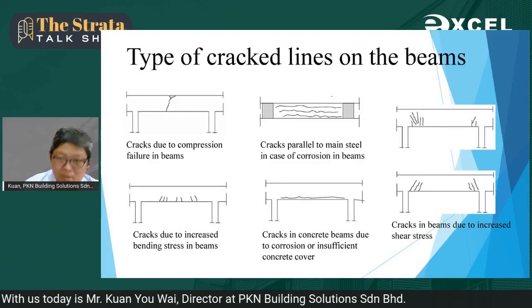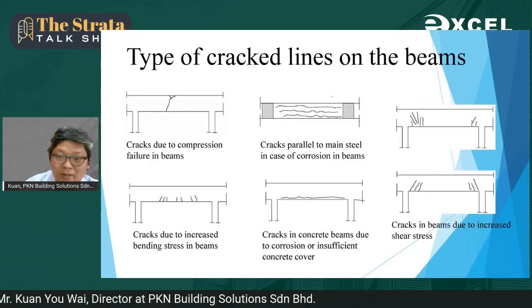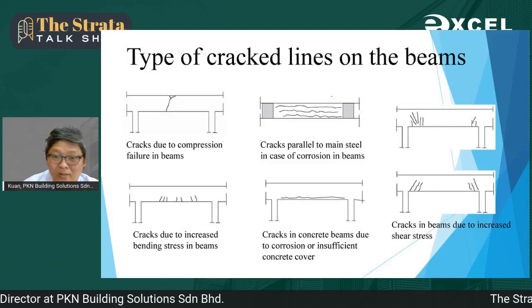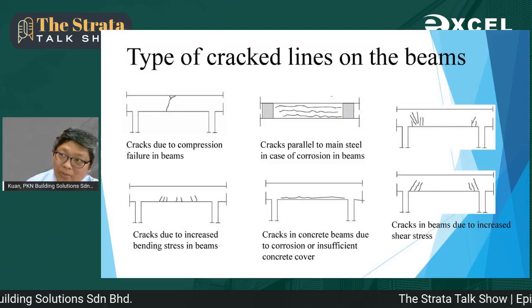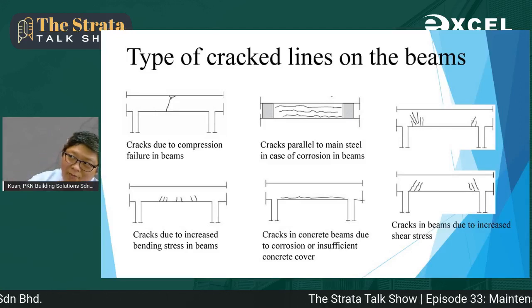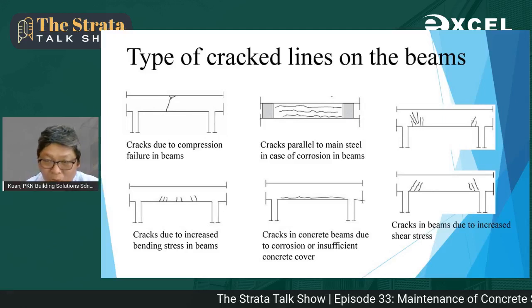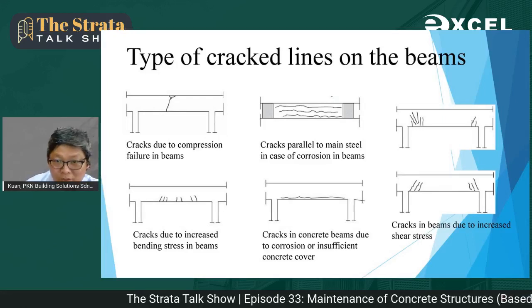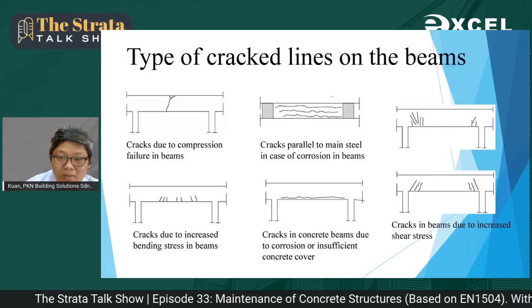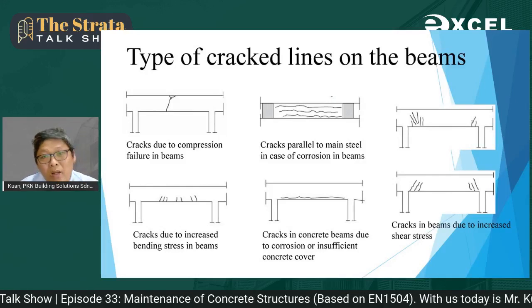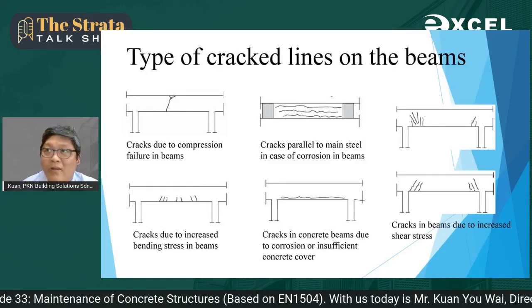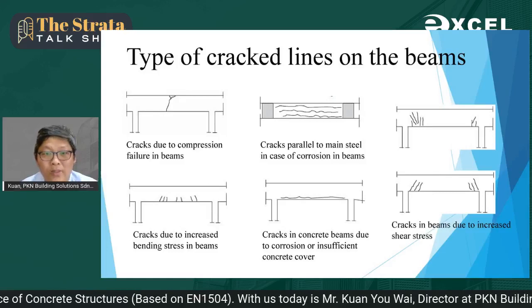The most dangerous one is shear crack. Shear crack can collapse anytime. The crack actually happens from the front and the back. It actually extends all the way through from the tension zone to the compression zone. This type of crack can collapse anytime. I urge you to look into this type of crack and get your structural engineer to come in for an assessment.